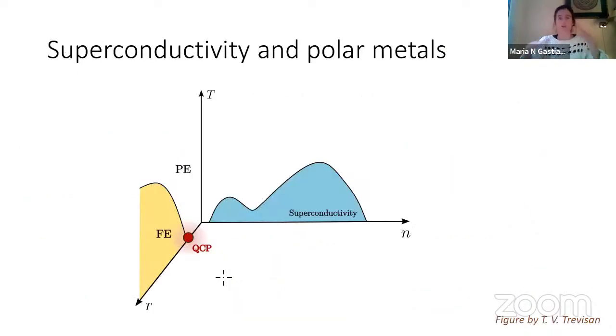So with that, I'll go into a bit of an intro of what polar metals are, because sometimes people think of ferroelectricity just in the context of an insulating material. So this would be maybe like a phase diagram for strontium titanate. You have temperature, and some parameter that you tune when you are in the insulating phase. This can be isotope substitution, it can be adding a little bit of calcium, it can be applying some pressure to your sample and so on. You can move the system closer to this ferroelectric phase. And then once you dope the system, you add carriers, and this system becomes superconducting.